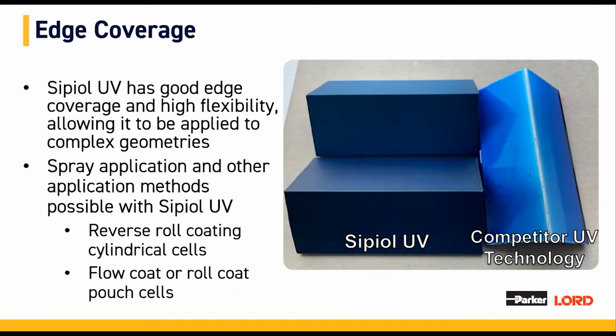Sipiol UV was specifically formulated to provide good edge coverage and to have high flexibility, allowing it to be used on complex geometries where other coatings or tapes may fail. As you can see in the image to the right, Sipiol UV provides full coverage on the 90 degree bend. The competitor, however, shows edge pull, exposing the metal substrate, leading to poor dielectric protection on the corner. Also note the pooling of the competitive coating at the bottom of this panel.